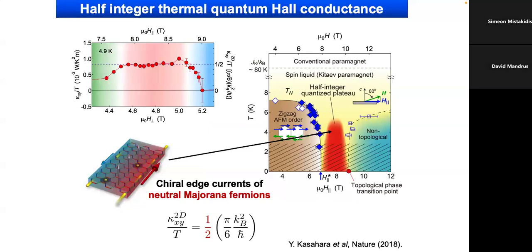A group out of Japan measured something called the quantized thermal Hall conductance. Essentially, when you apply a magnetic field to ruthenium trichloride, you can suppress the magnetism. And then there's this region here in red, where it's believed to form some sort of a spin liquid. People are arguing what kind of spin liquid it is. And this group claims that in this region in red, they observe a quantized thermal Hall conductance. And that's been a very controversial result. There have been probably 10 or 15 papers now arguing about this back and forth. These are very difficult experiments.